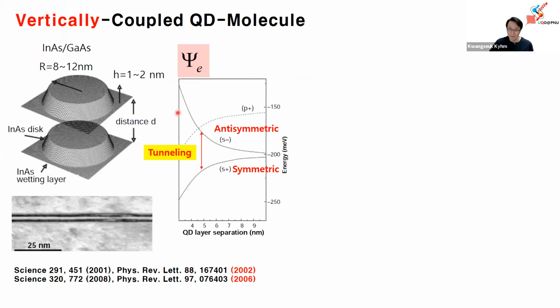Coupled quantum dot is a bit of an old issue. It was proposed back in the early 2000s as a building block for quantum manipulation. Initially, vertically coupled quantum dots were proposed. If the distance between two dots is, for example, several nanometers, tunneling induces wave function overlap, and a symmetric electron bonding state and an anti-symmetric anti-bonding state can be formed. The distance can be controlled by changing the thickness of the barrier between two dots, and then theory and experiments can be compared.